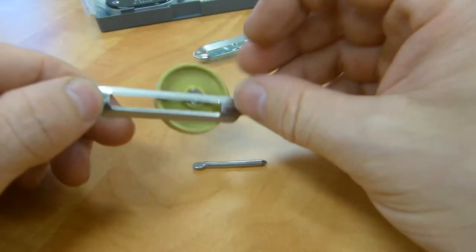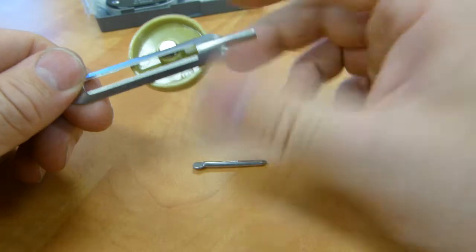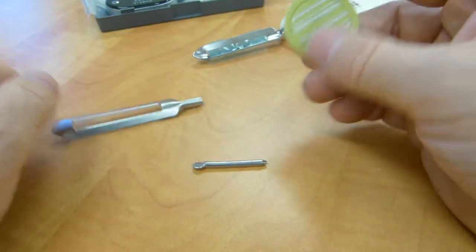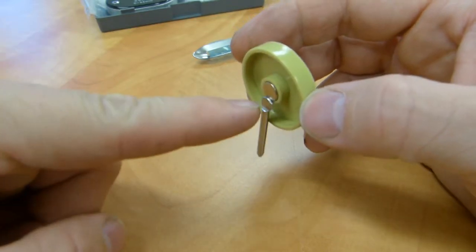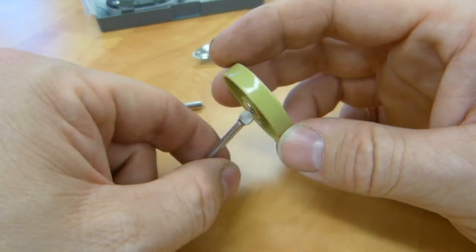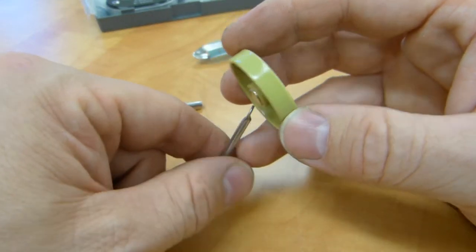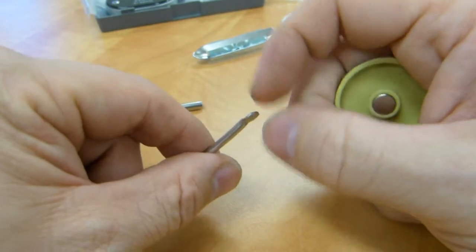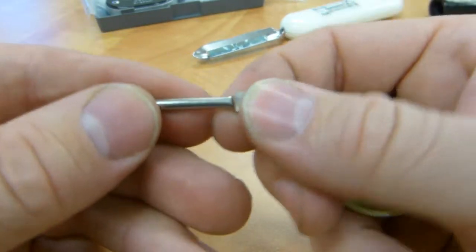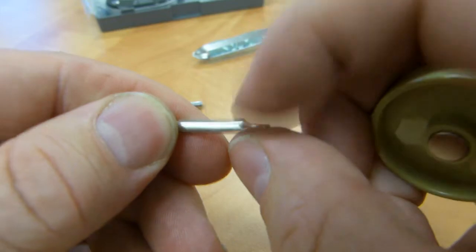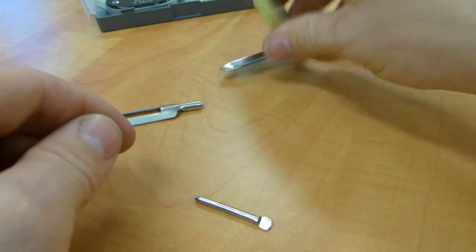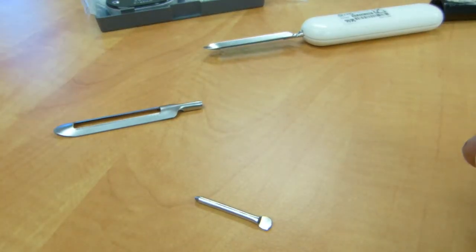This one is a pin that's absolutely not magnetic except just the end of it here very slightly. That magnetism is a result of pinching the end of the pin and it's undergone some cold work and some plastic deformation and it changed the magnetic properties. The new one is also magnetic so that's made of the same steel.